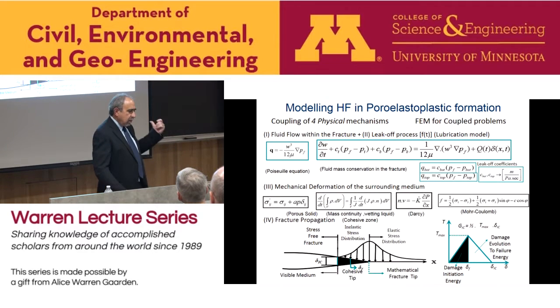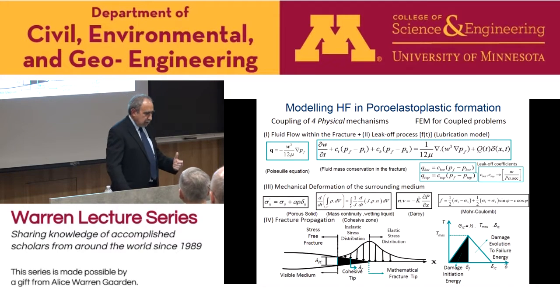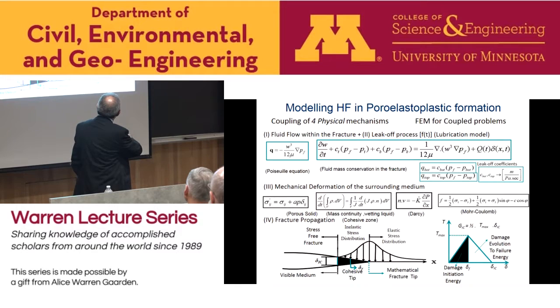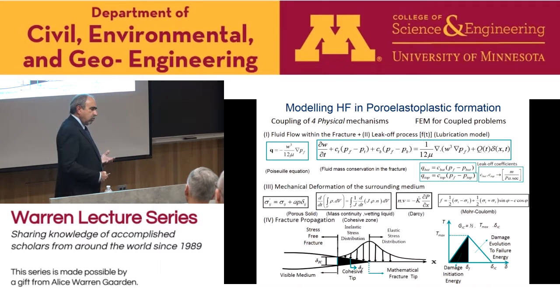And we extended this, the results I presented before were for dry rocks, okay? Then we extended the results to elastoplastic rocks. Basically, we modeled also the leak off of the fracture fluid from the formation and the diffusion of the fluids and the pore pressure in this modeling. And we used Abaqus for this modeling, used by one of my PhD students to do this calculation. We thought to go to Abaqus because it has better solvers, better interfaces, geometry, but it had also limitations. With Abaqus, for example, we couldn't model the fluid lag. And the other thing also, that was the cohesive model.